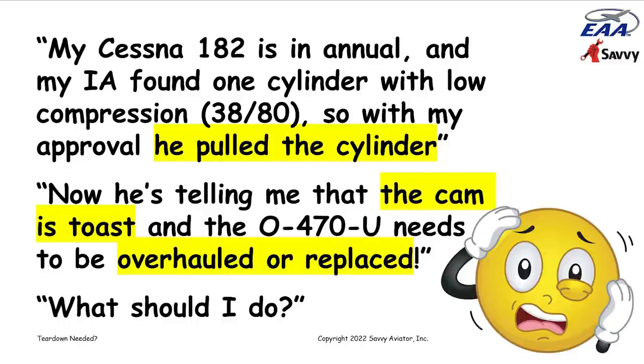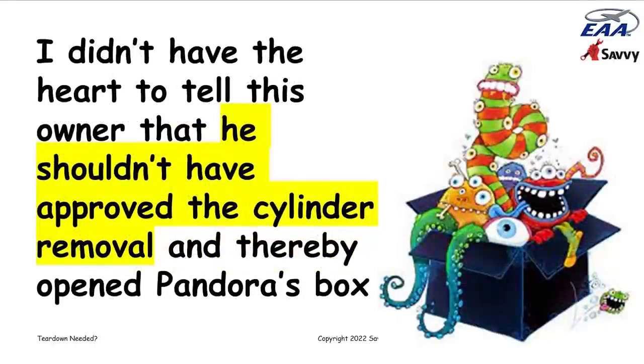What should I do? Well, of course, I didn't have the heart to tell this owner that he shouldn't have allowed the cylinder to be removed just because it was 38/80. We talked about that in the webinar last month that was titled Cylinder Rescue. And typically, if you have a 38/80 cylinder and you do what Continental says, which is go fly the airplane for an hour and then test it again, the reading will typically come up 10 points and it'll pass the test. But even if it doesn't, you look at it with a borescope. If the valve is leaking, you lap the valve. If the rings have a problem, you do a ring flush. But almost certainly that cylinder didn't need to come off.